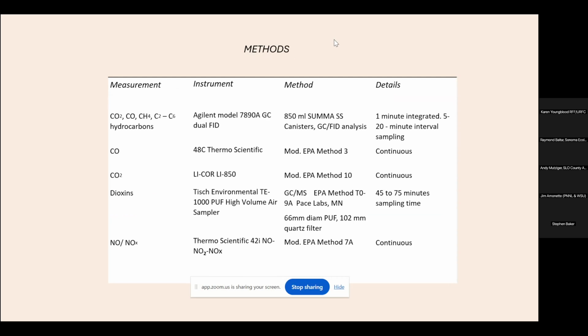We did continuous measurements of CO, CO2, NOx, black carbon, and PM 2.5. And then we collected smoke in canisters, and we did that at intervals based on the rate of consumption of the fuels. So we collected at a lot shorter intervals during the flaming phase when there was a high consumption of fuel, trying to get some estimation of a good weighted fire emission measurement for the whole fire. Because if you just average all the samples together, you really don't get a very good average, because a lot of the fuel is consumed in the first few minutes, and then as it burns down, you get other emissions, but that doesn't represent as much of the total fuel being consumed.